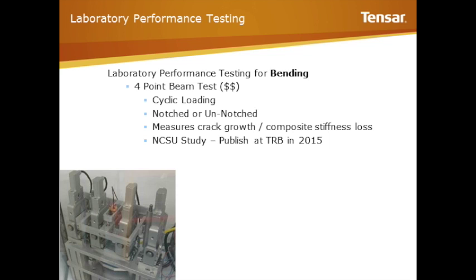And so how do we evaluate that? Well, the 4-point beam test is a pretty good indicator of performance in this type of situation. And those of you familiar with the test know it's a cyclically loaded test, so you're not just applying continuous pressure. You're loading it as you would in the field with traffic. And typically the test is done unnotched, but in this particular case, to evaluate reflective cracking, we notch it. And because the performance of these composite systems is so good and could take a couple of days to run, we increase the strain levels. So you're typically doing strain levels that represent a thin residential street. So those sort of load levels under a standard heavily weighted truck axle load. And so we're putting it under a very aggressive torture test type condition, and we're looking at both crack growth or composite stiffness loss, evaluating to what extent the interlayer can benefit that.